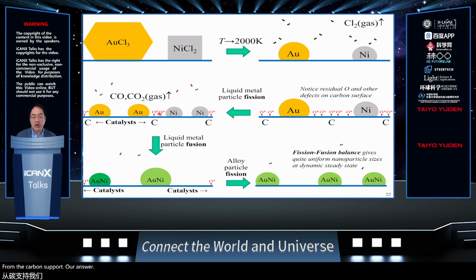And so it starts to move around to hunt for these carbon groups on the surface, and eventually can fuse with the gold to become a gold-nickel alloy catalyst. But this also has some catalytic activities. This can also split. And so you have this balance between nanoparticle fission and fusion. So you get a dynamic steady state, as long as there is oxygen and carbon to be catalyzed.